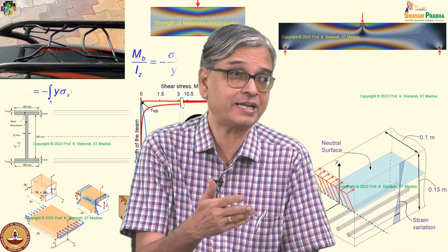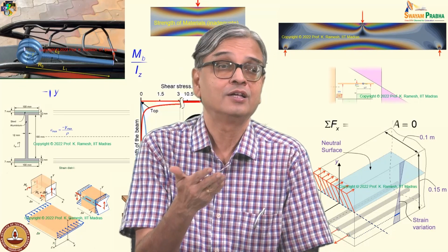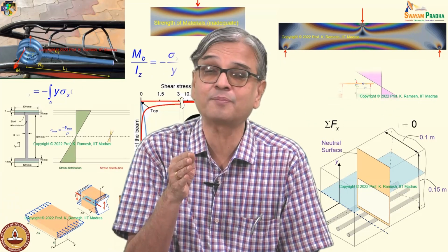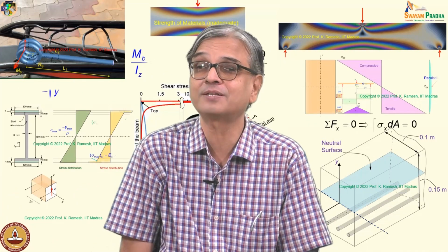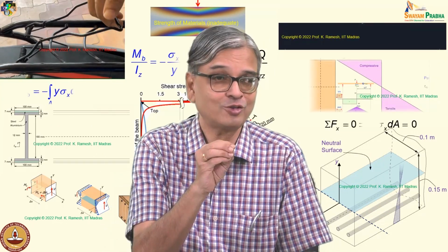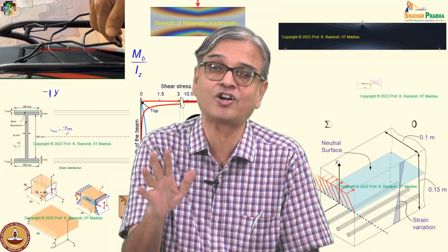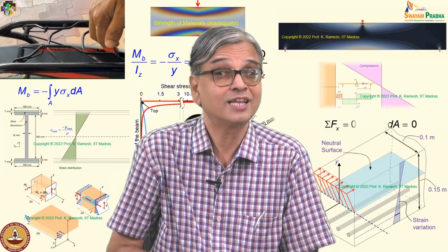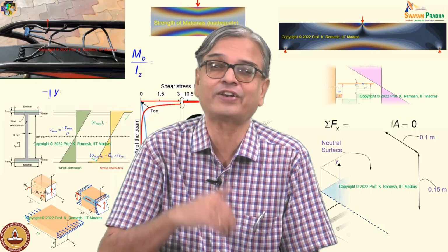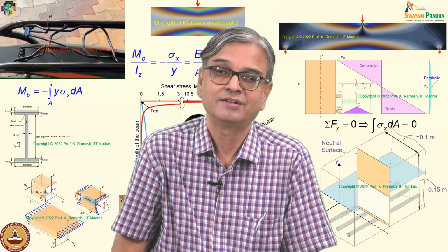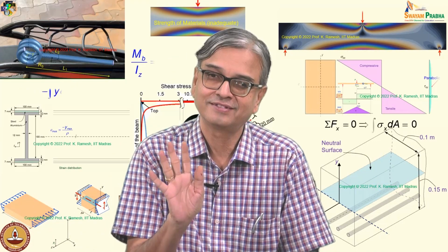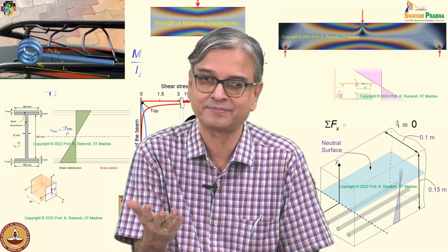See, one of the very important applications is you should know the bending moment diagram, so that you find out which is the tension side, which is the compressive side. You should not put the steel bars in compressive side and say that you have reinforced the beam. The whole building will collapse. And they have also narrated one instance, somebody made the concrete beam without even putting a reinforcement. Now you have an alibi. How do I reinforce? Suppose somebody has made a mistake and you have to do retrofitting. What can I do? I can bond a steel beam in the tension side firmly. That is one way of alleviating the problem.